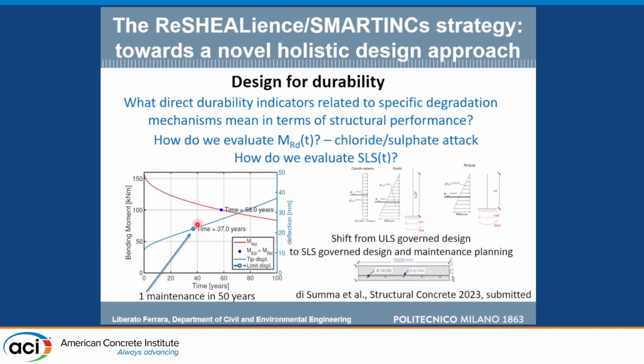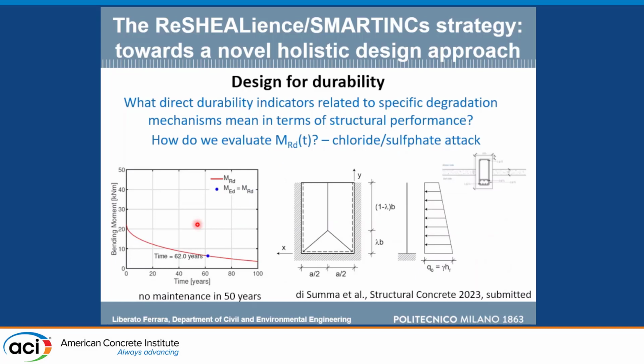And we realized this. For example, surely the durability is extended, but also we realized that probably it's no longer the ultimate limit state which governs, but the serviceability limit state, because you have slender structures which are more deformable. We said when the deflection reaches 10% of the thickness, it's already too much deformed, so you have to probably intervene. But still, in this case, for the slabs, we used the yield line analysis, because you have to design in a two-dimensional way, and estimated the service life.